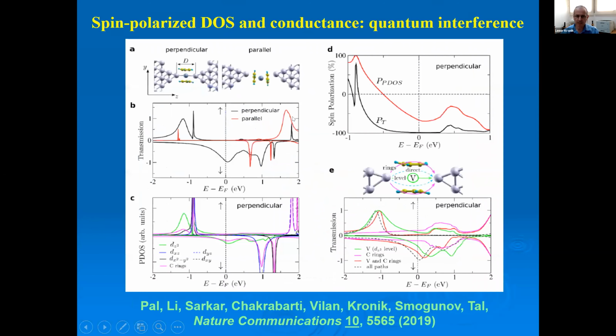So the remaining issue theoretically, and this would be my final slide, say for the conclusions, is to show where this comes from. So first of all, it's not clear a priori whether the molecule is absorbed in or is captured in the junction in a parallel or a perpendicular configuration. So we computed both, and then we computed the transmission for both. And we saw that there is a significant spin polarization in the transmission for the perpendicular configuration, but not for the parallel one. So we believe that when we see spin polarization in experiment, it's because of the perpendicular scenario.